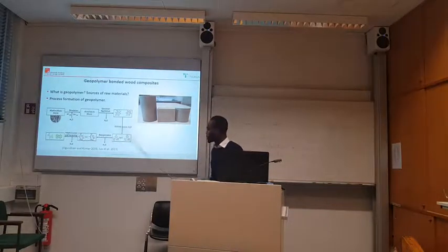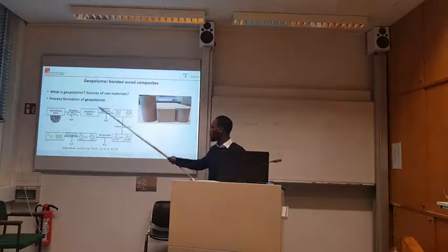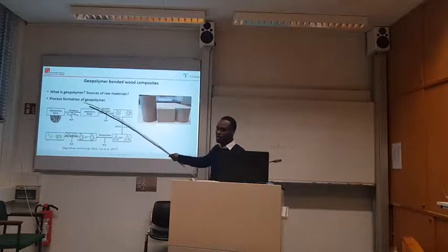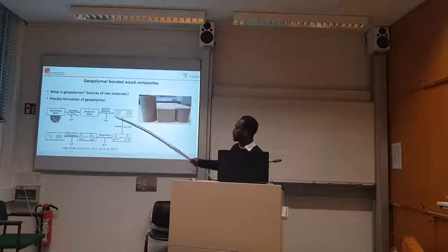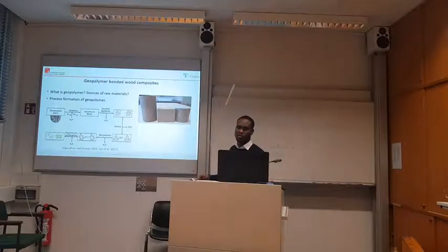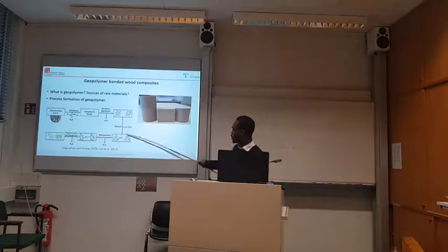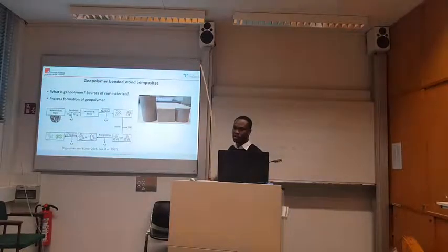But with this material, in the beginning, we are using water in the dissolution and the hydrolysis and the species equilibrium. So in the dissolution, we are using water. But after the dissolution process and the hydrolysis process, we are now eliminating water from the system because we don't need water in the product. The water needs to come out so that the product can bind. Then it goes through the gelation, still in the gel form, and the reorganization is still ongoing. The atoms are rearranging in a specific way.